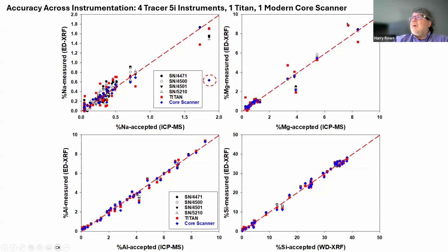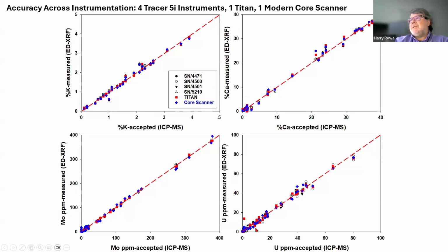And to kind of beat a dead horse, that core scanner that I showed you earlier, we did the calibration for that. And again, everything nicely fits along here. Imagine that you had 100 wells with 100 data sets, all analyzed by the same instrumentation, or even a variation here, but with the same calibration. To be able to go back and relook at all these data sets, maybe do a regional study, and not immediately be confronted with the inconsistencies of it. Incidentally, this also looks really good because the same 2 physicists designed all of these instruments. So the same concepts carried themselves through these 6 instruments.